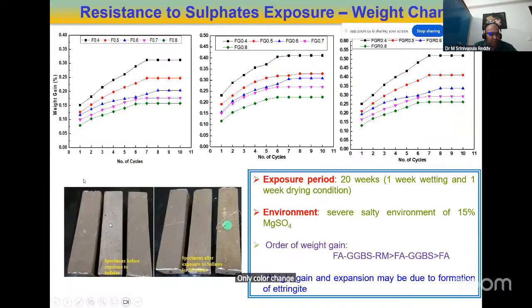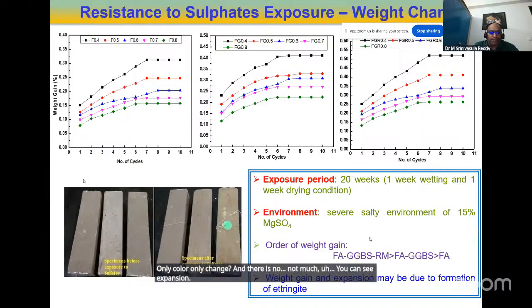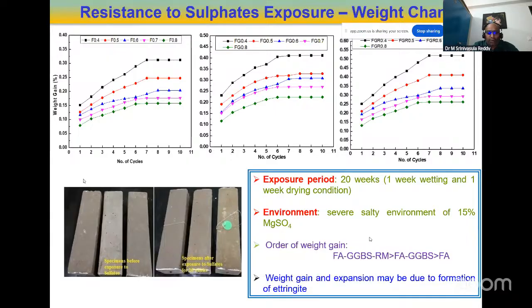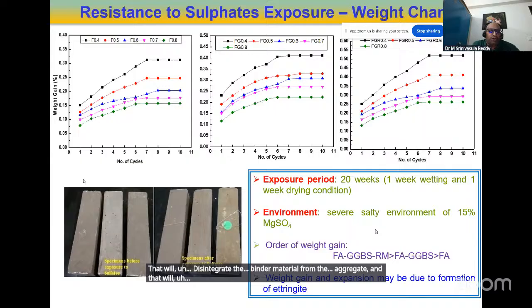but you can see even in the same members only color changed, and there is not much expansion, and a little bit of weight gain is there. That is maybe due to formation of ettringite. If more formation of ettringite is there, that will disintegrate the binder material from the aggregate, and that will lead to loss of strength and loss of material.